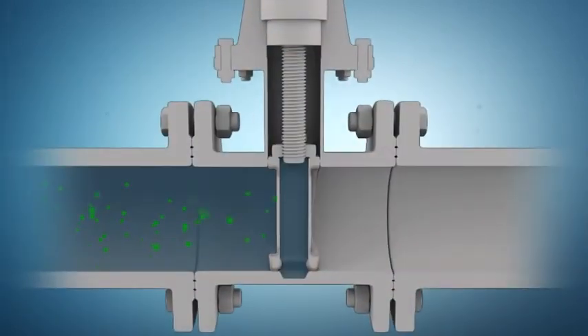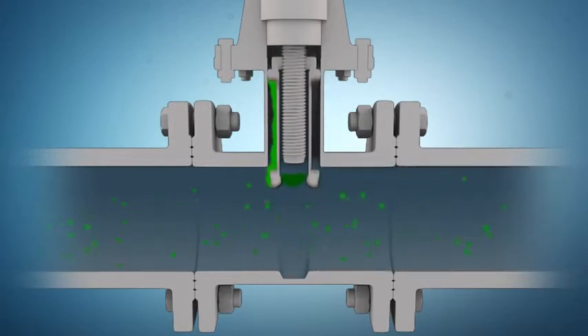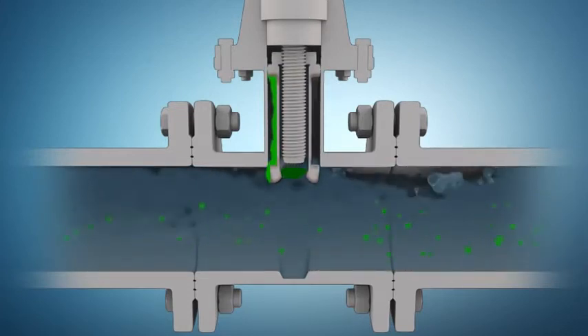The rubber quality is crucial for valve durability. If the bonding is insufficient, creeping corrosion will occur. If the resistance to water treatment chemicals is insufficient, cracks and other damages will occur. If the formation of biofilm is not taken into consideration and if the stem hole in the wedge is narrowing at the bottom, bacteria will grow and cause contamination of the drinking water.